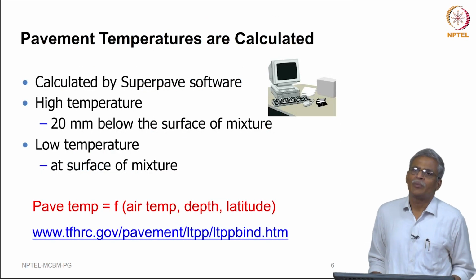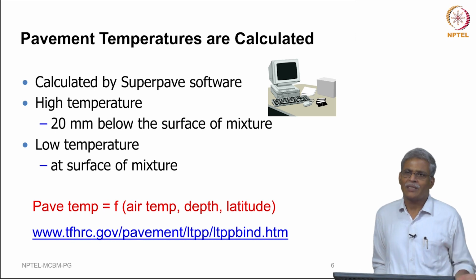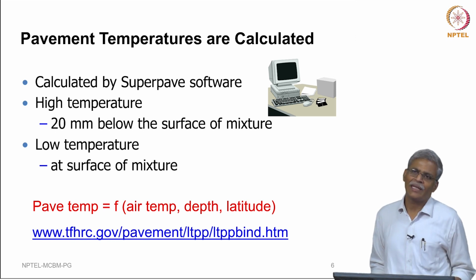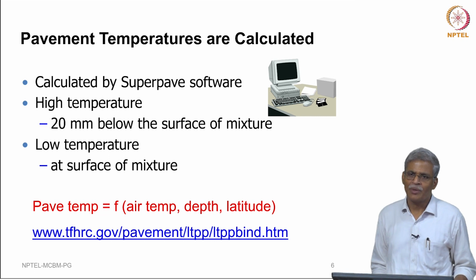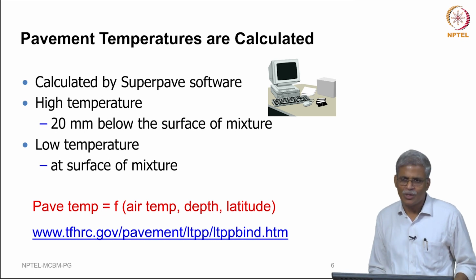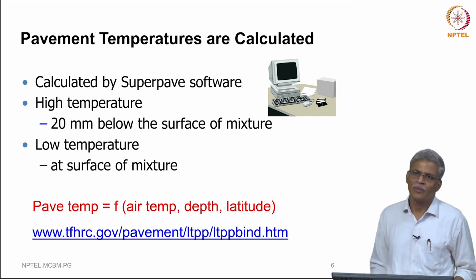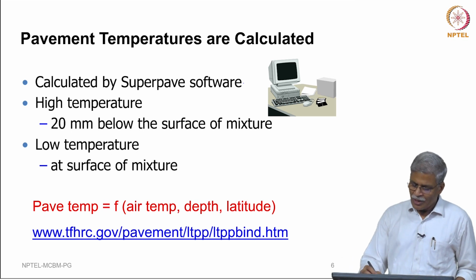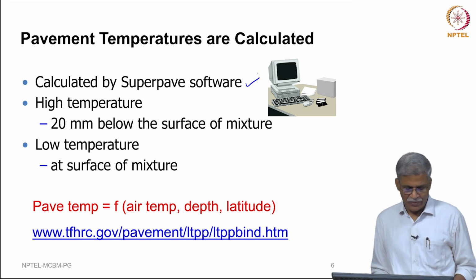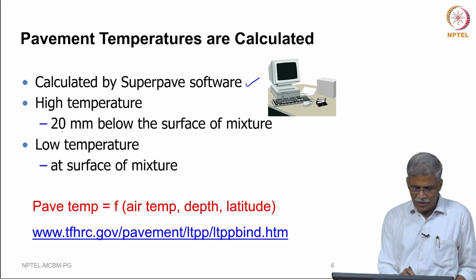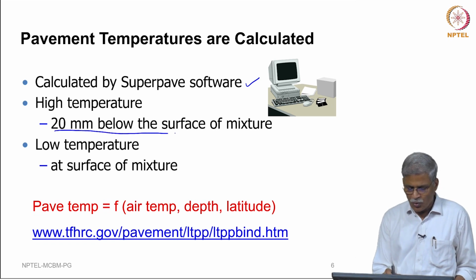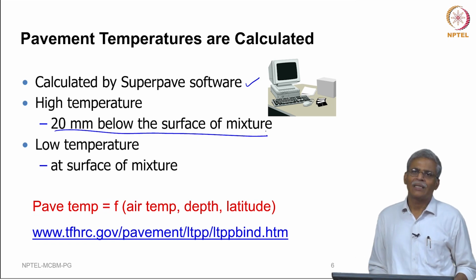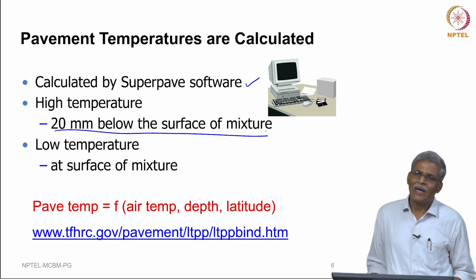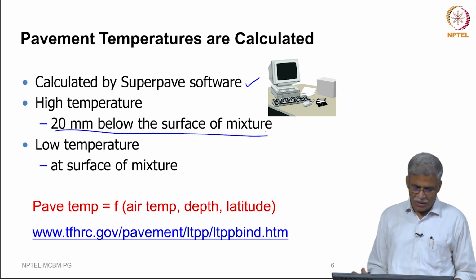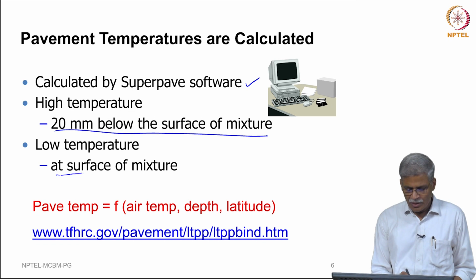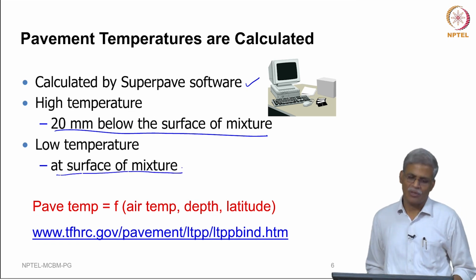how do we do this pavement temperature? Now we realize that one should have a very clear understanding of the pavement temperature, and only then can we actually use this performance graded system. So you can use the Superpave software that is available, and for high temperature you will need to find out the temperature of the mix 20 mm below the surface of the mix, and for low temperature this is taken at the surface of the mix.